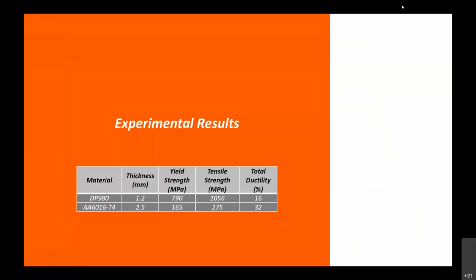We picked two materials to diversify the results. The first is a popular advanced high strength steel — DP980, a 1 GPa material, 1.2 mm thickness, commonly used in automotive. It is not very ductile and its high strength means high springback. The second material is a standard 6000-series aluminum, automotive grade for external panels, 2.5 mm thickness, more ductile than the DP980. These two materials show different levels of strength, ductility, and Young's modulus.